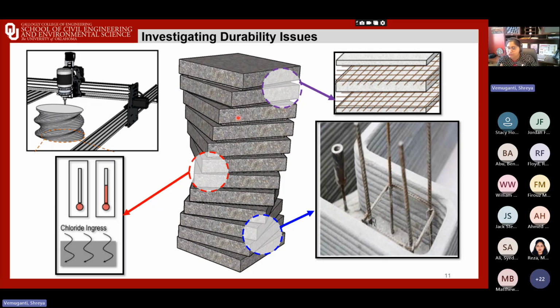Unlike traditionally cast concrete, which tends to encapsulate the reinforcement because you have that cover, and also the formwork, which from the beginning is protecting your concrete during the setting and hardening process, printed elements are formwork free. Therefore, it seems possible that there could be potential pathways for ingress. So in concrete 3D printing, this is something we need to think about because the entire element, as you can see here, is layered interfaces. This is a little more exaggerated so as to show the interface itself.